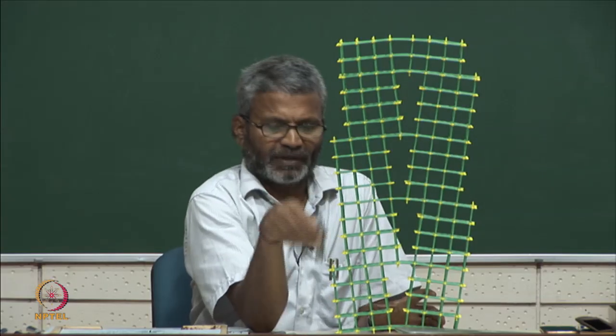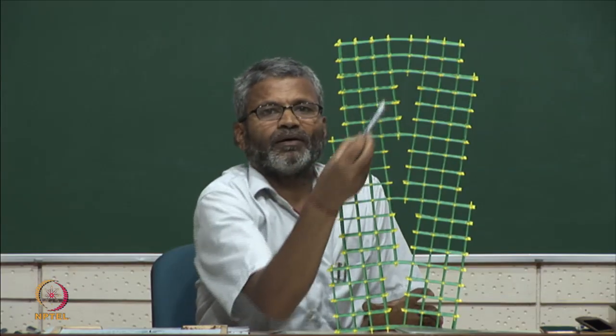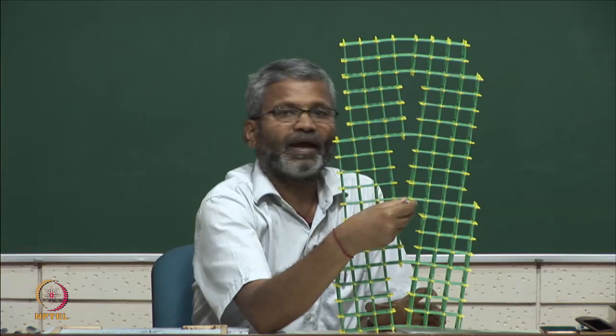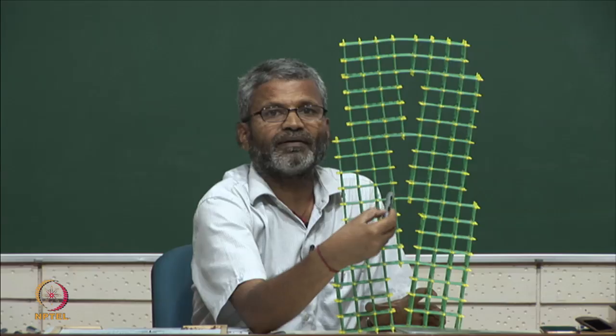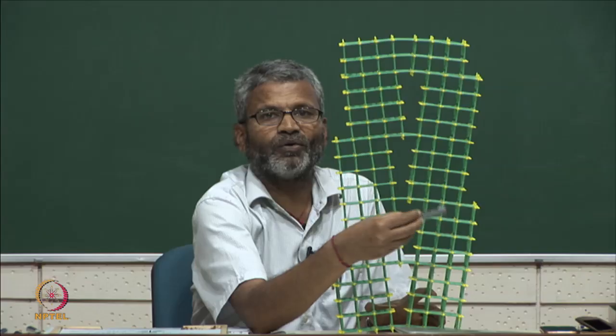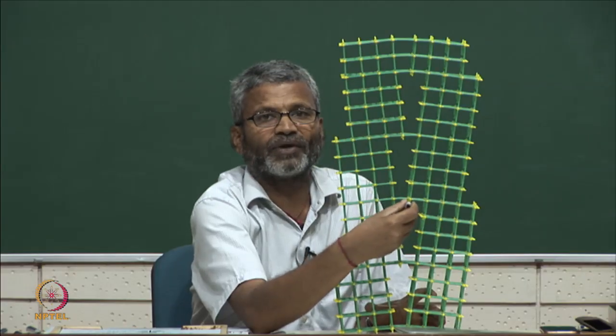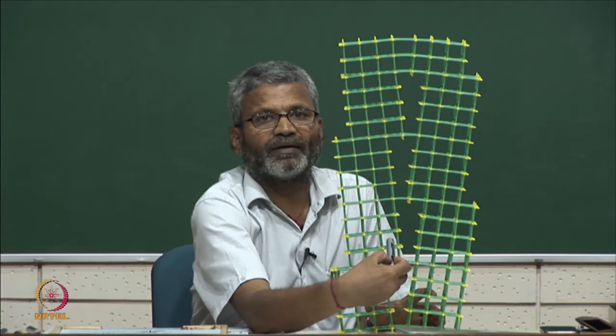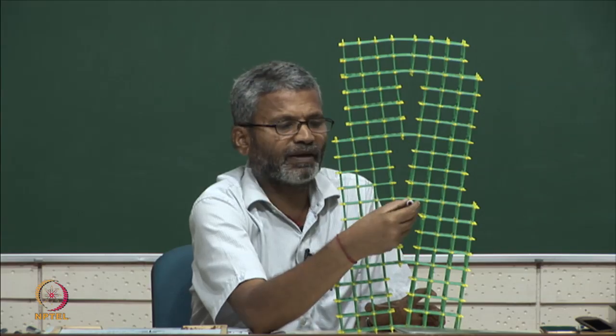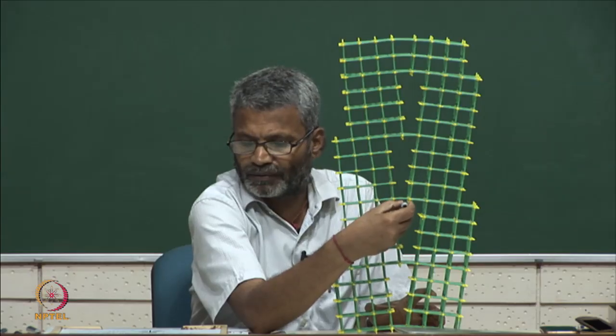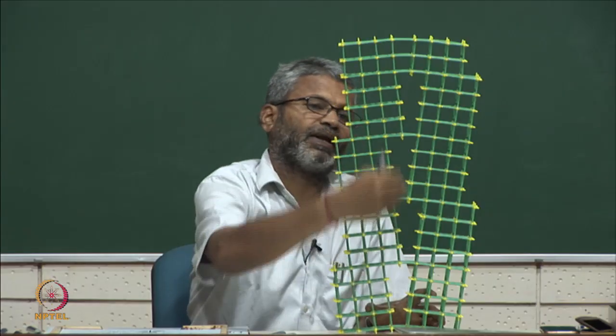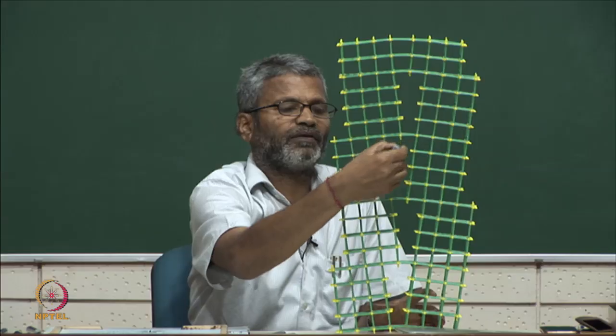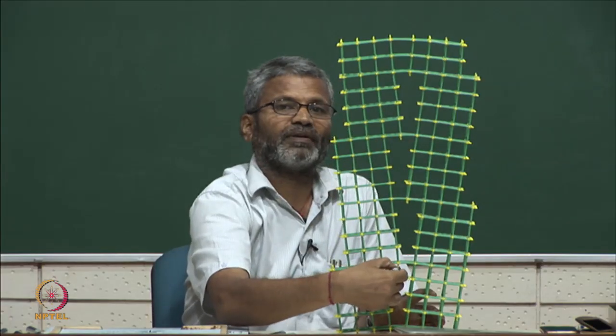The tilt angle is not very small here, but you can see the configurations close to the boundary. If you look at this plane, it comes and abruptly ends here, but the neighboring planes continue. Locally here you have an arrangement like an edge dislocation, because this plane abruptly ended and the neighboring planes continued going down — this is like an extra half plane. So a vertical symmetric tilt boundary can be considered as a series of parallel edge dislocations lying in the boundary plane.